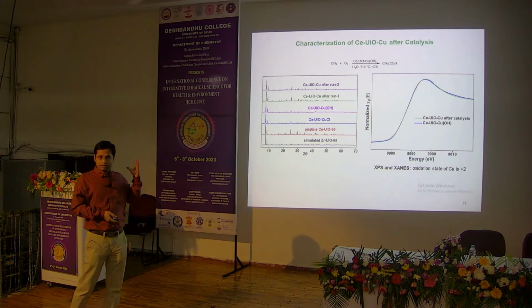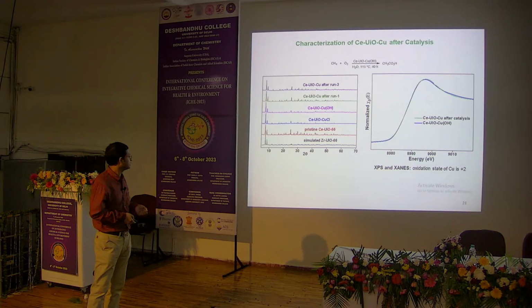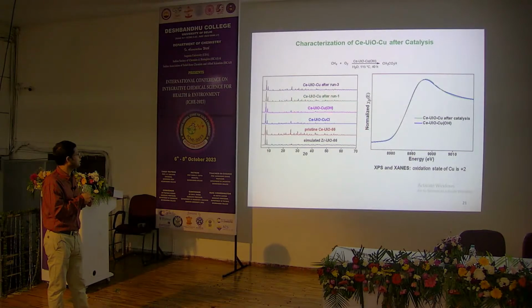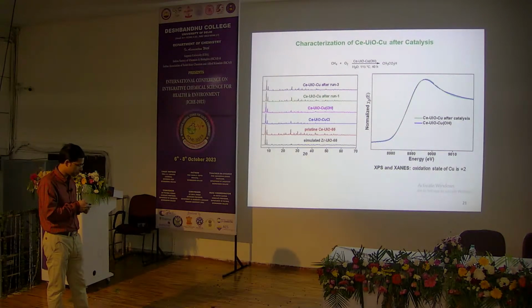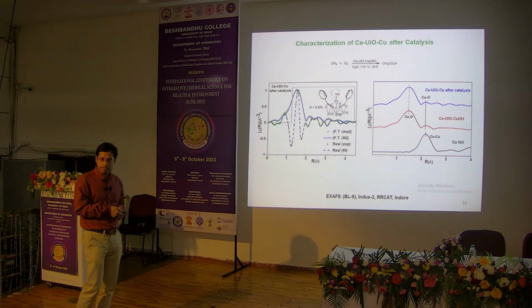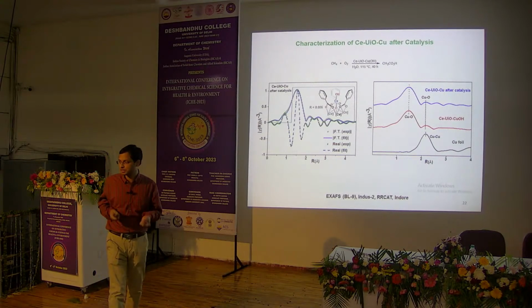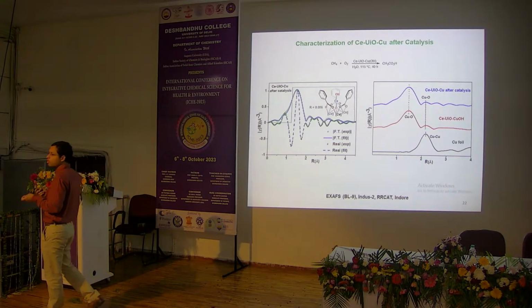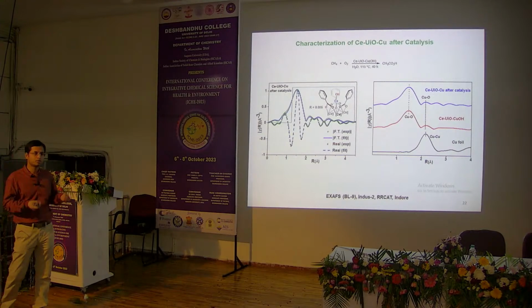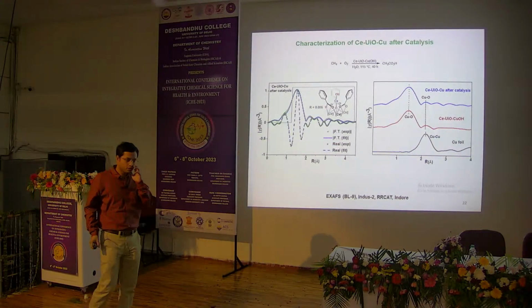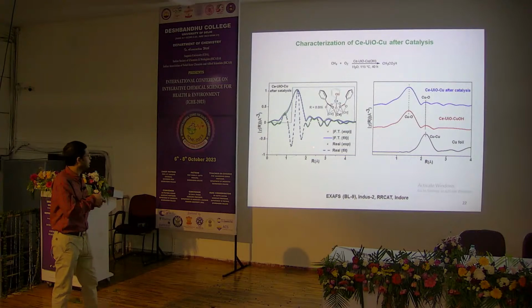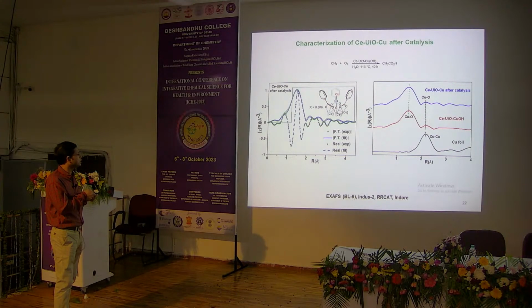and that CO might be a reactive intermediate. We also characterized the MOF species after catalysis, and we found that even after the catalysis, the structure remains the same. The copper is in the +2 oxidation state based on the XPS, and this is the XANES spectra. And the resting state, that is the copper species that we get after recovery of the catalysis. After the catalysis, what are the species we get? That is called the resting state.